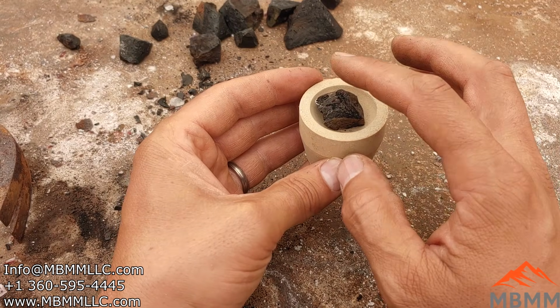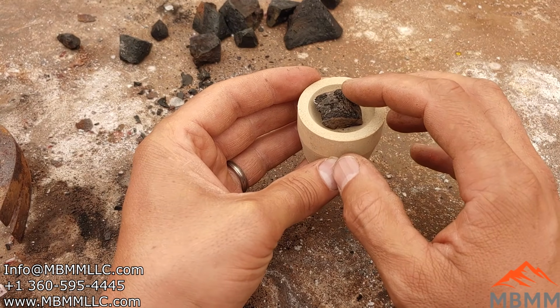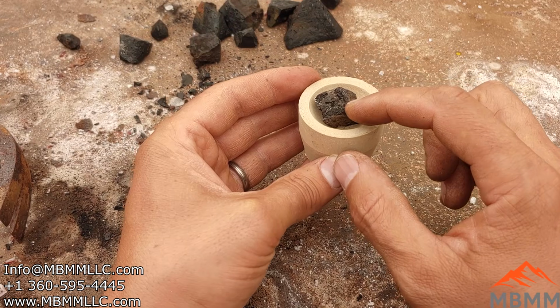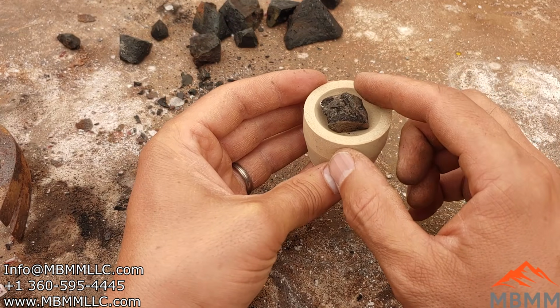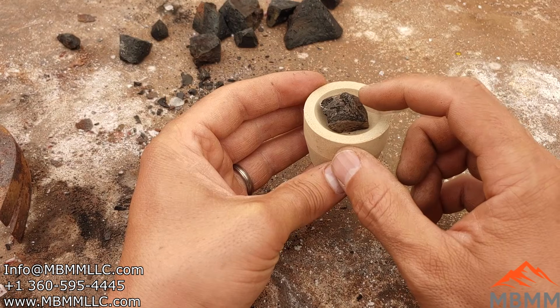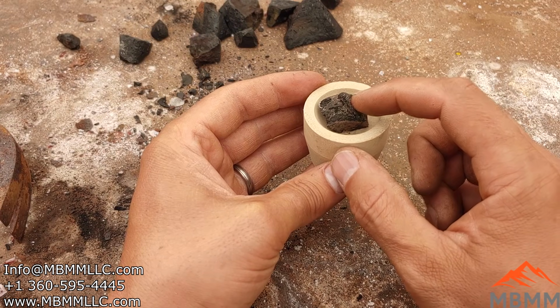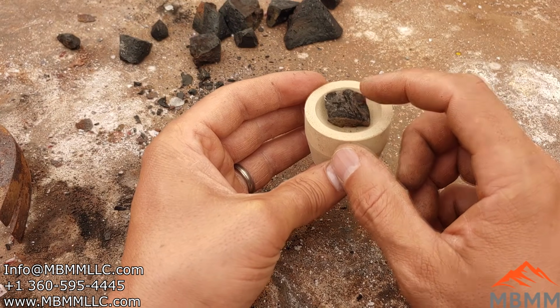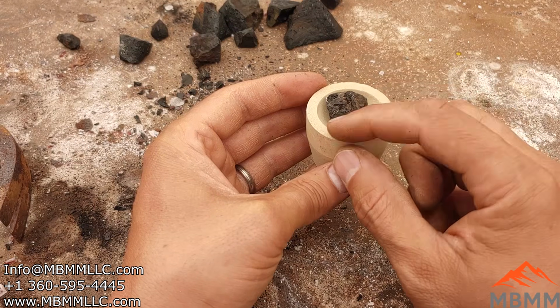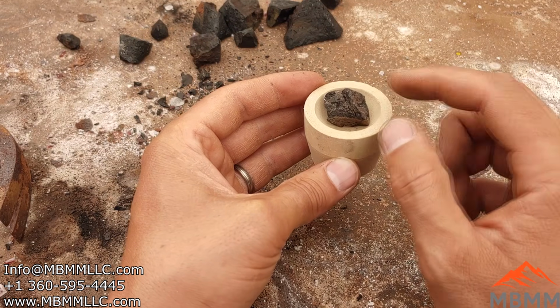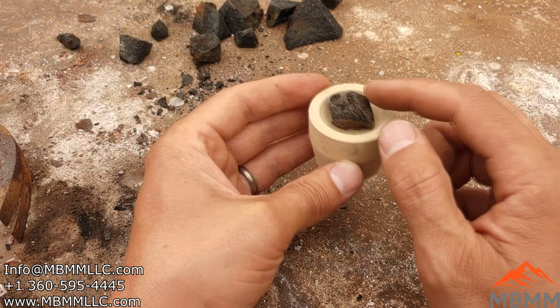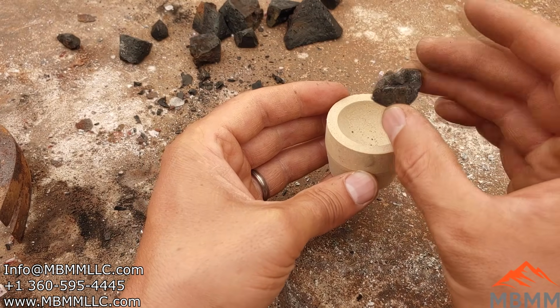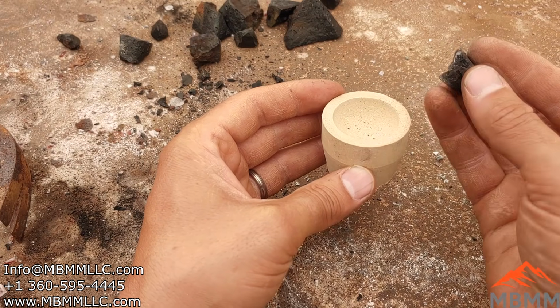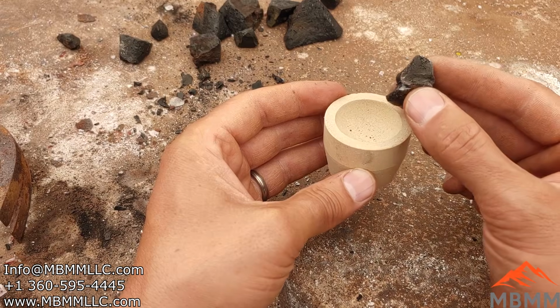But what this does is, when I put it in the furnace at 1800 degrees, the lead melts and then it heats up, and about 1650, I think, the lead oxide that forms on the surface of this thing in the furnace starts to melt, and the lead oxide will run off and be absorbed by this cupel, and that process continues until all the base metals are removed from the lead puddle, and all you're left with is going to be your gold and silver.